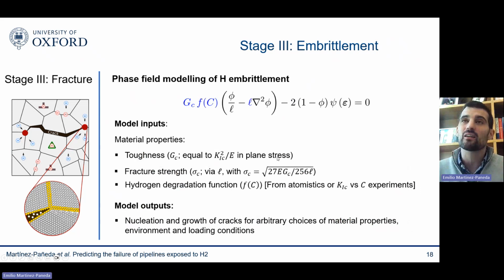So basically what this means is that at the end of the day, this model for embrittlement, the only input coming in is the toughness of the material, which you can get from the fracture test. For example, for plane stress, we know that it's equal to the fracture toughness to the power of 2 divided by the Young's modulus. The fracture strength, which comes into play in the model for the length scale. This is the closed form expression. So strength is a function of Young's modulus, fracture energy and length scale. And then we have this hydrogen degradation function, which can come from atomistics or from experiments on toughness versus hydrogen concentration. And this is the case I'm going to focus on here today.